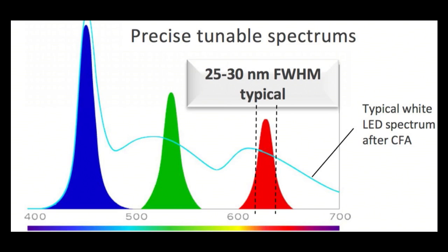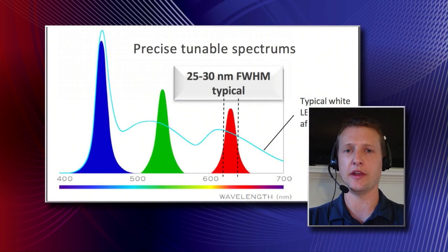And it's usually 25 to 30 nanometers for cadmium selenide quantum dots. It can be broader for other types or narrower depending on their exact composition and properties. But that's a pretty typical spectrum for a quantum dot that you would use for a display that would give you then really high color gamut for the final display that the viewer is seeing.